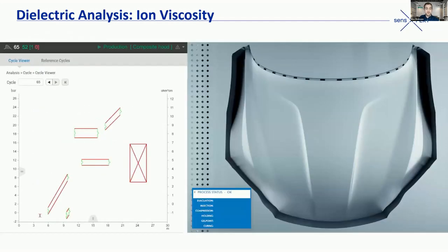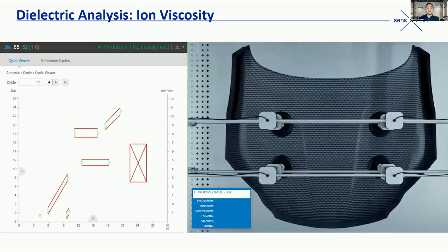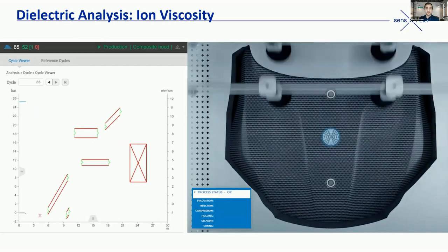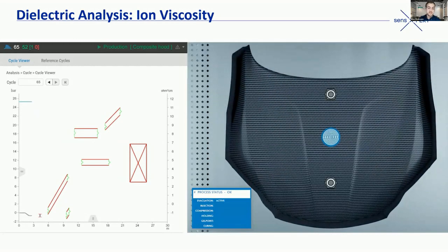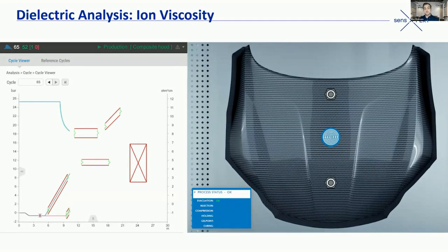So this is another really quick video just showing what this looks like in process. Again, the same resin transfer molding. Here we have 2 pressure transducers and a dielectric sensor in the center. The dielectric sensor, that ion viscosity, is measured on the top line there. So the top line is the dielectric signal. The 2 lines on the bottom are the pressure transducers. So you can see as the mold fills, the resin comes in contact with the sensor. Here you can see it's dropping down and reaching a minimum viscosity.